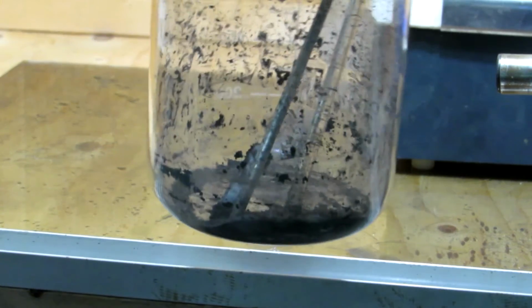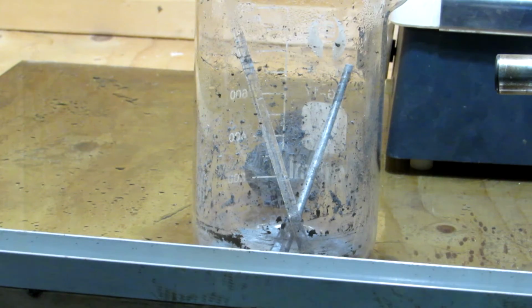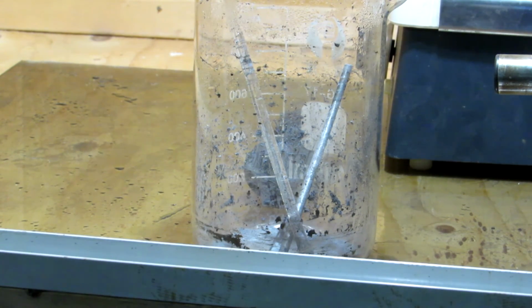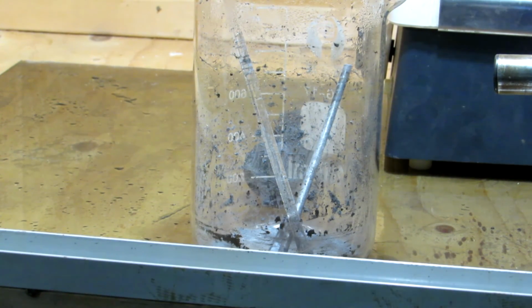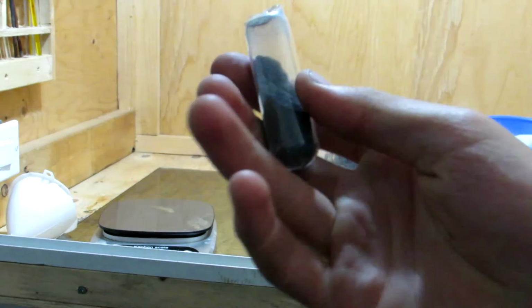is one very easy way to test for zirconium, and this is by simply burning it in a flame. Zirconium burns in a flame with a yellowish to white color, and sparks are emitted as it burns. This is very characteristic of zirconium, and it's actually used in some fireworks, interestingly enough, for this effect. So as you can see here, we have a little bit of zirconium, and upon dropping it into the small blowtorch, it's very evidently releasing some nice sparks. So this confirms the presence of zirconium metal here, and from all of that we got around 8 grams of zirconium, which is pretty good.